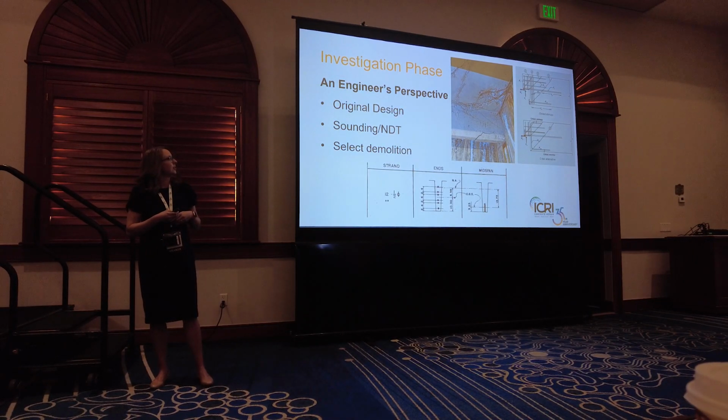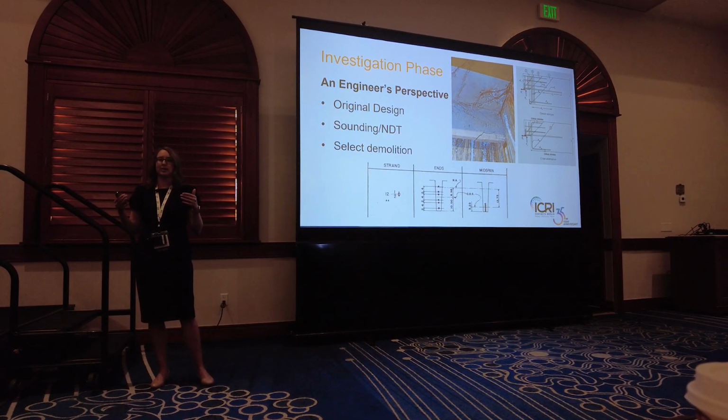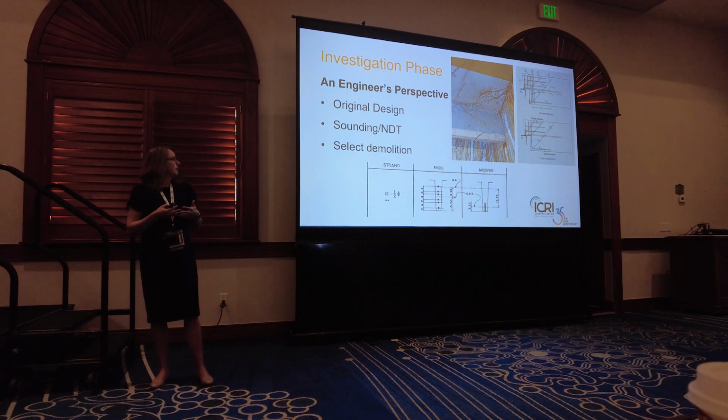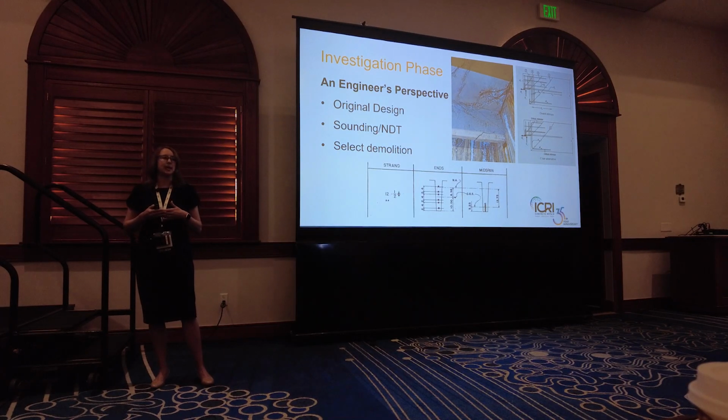For example, the diagram on the bottom shows pre-stressing strands in just one layout that there could be, but there are many different patterns. You can have your pre-stressing strands going straight through the member, or you can have them harped, where they come down at a point at the middle. That's what this example is showing. You can try to determine that using GPR, but that's often not very accurate, and it just looks like a blob of steel. X-ray is really the most accurate non-destructive testing method to figure out your pre-stressing strand layout.